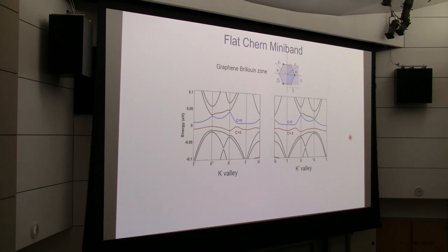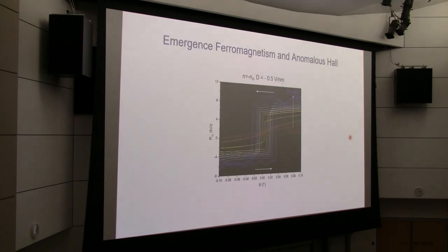However, because these bands are not only topological but also very flat, you can imagine when you dope holes into the system, it's possible to break the symmetry due to strong correlation. For example, all the holes go to one valley, and you then will have a magnetic state, but also a topological Chern insulator state. And luckily that indeed happened in the real system. Again, working together with Professor Gordon, we were able to show that when you put one hole per lattice site, the system automatically develops a magnetic hysteresis.